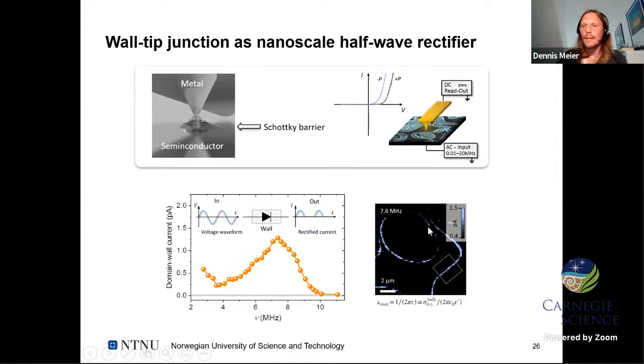This is only happening at the position of the wall, so we are really doing this rectification only at the position with the tip and the domain wall. This is controlled now, where this drop-off frequency is, by the local conductivity. That means that different walls with different conduction also have different drop frequencies.